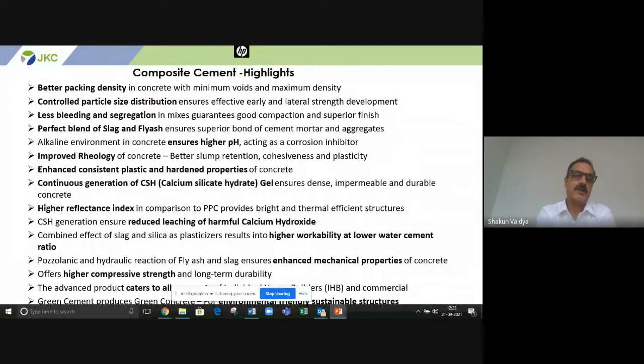It is a perfect blend of slag and fly ash because silica and lime complement each other. And improved rheology, enhanced consistent plastic and hardening properties of concrete are achieved in this cement. It is a continuous generation of CSH gel. So as and when this process goes on, it will go on further reinforcing the exposed concrete structures, and this gel will further make the concrete more impervious and watertight in nature.